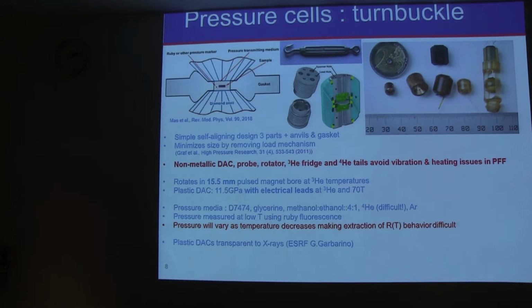To reach the highest pressures possible, we need the two anvils to be perfectly parallel together. So most pressure cells have various aligning processes, various screws, and those pressure cells can be pretty big. But for the magnets, the sample space is rather limited. We have about 32 millimeters for static field, in which we have to fit absolutely everything. We have to fit the probe, the cryostats, and the pressure cell. So Stan Tozer, my mentor, developed a pressure cell based on the turnbuckle principle.